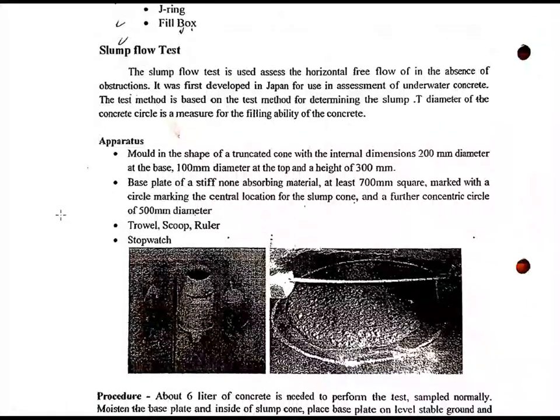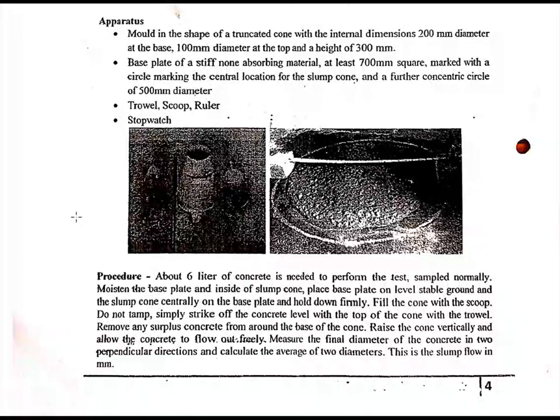So for the slump flow test, we need 6 liters of concrete, and it should be poured into a slump cone. You have seen the slump cone in our laboratories. In the slump cone, you have to fill the SCC, self-compacting concrete, without any compaction. Fill it, strike off the top surface, and the area around should be clean, and then you lift the slump cone vertically upwards. Your concrete will start flowing. The moment you lift the slump cone, you need to start the stopwatch, and the moment it stops, you stop the stopwatch.